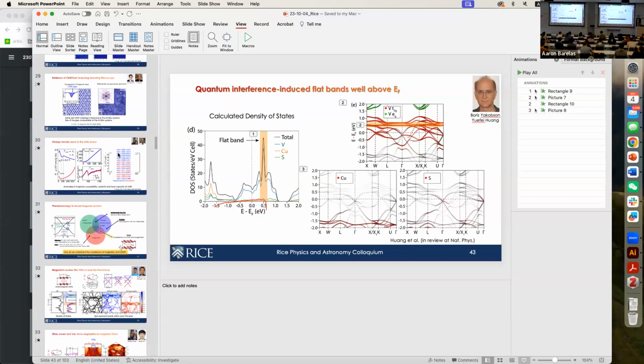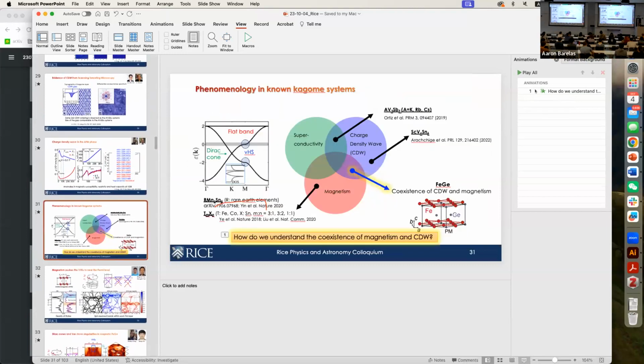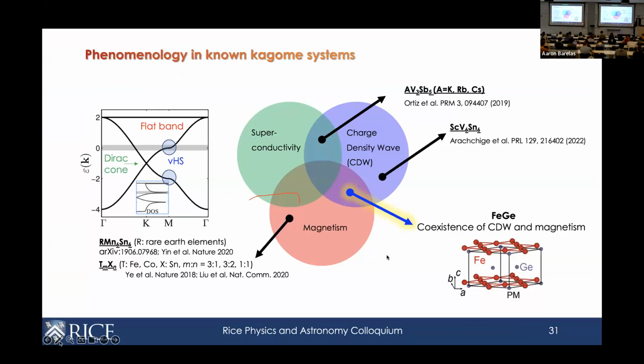So essentially, if you think about this simple, naive, and likely wrong theoretical picture of magnetic order: naively, if you have a flat band, this flat band will give you the itinerant magnetism. And it turns out, I don't know by coincidence or not, in all of these magnetic Kagome systems, if you calculate their band structure in a non-magnetic state, the flat band is always close to the Fermi level. I'm not saying that this is what's actually driving the magnetic order, because that's likely not true.